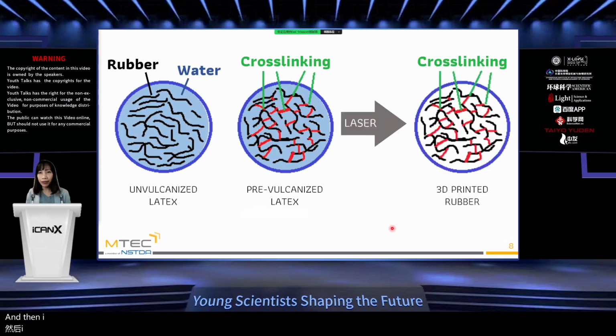And then I put that in the 3D printer, expose it with the laser, and evaporate the water out. So that will leave a layer that was exposed to the laser and without water, and it is actually a solidified natural rubber. So that's the process that I kept doing one by one on top of each other. And each of the layers I made is only 150 microns. So this process gives you very fine details, a very small feature for the printed part.